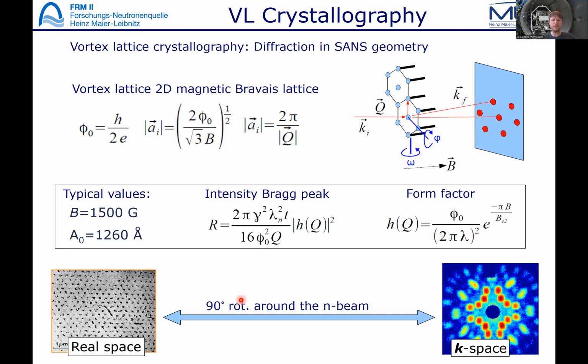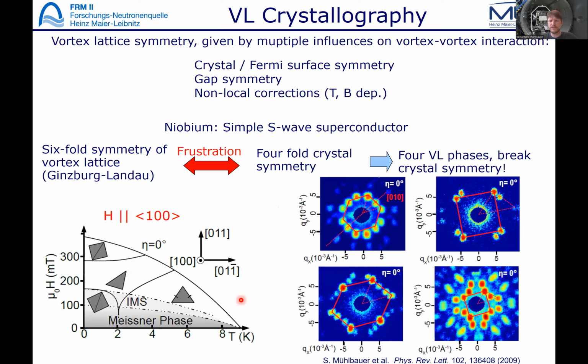So why is this useful? And this is one of my very last slides. Why is it useful to do vortex lattice crystallography, to look at vortex lattices by means of small angle neutron scattering? Well, there are multiple influences on the vortex lattice symmetry, and this is of course influenced by the vortex-vortex interaction. These influences can be the crystal or Fermi surface anisotropy. It can be the gap symmetry, so looking into conventional or unconventional superconductivity, and it can be non-local corrections, for example, that are temperature and field dependent.